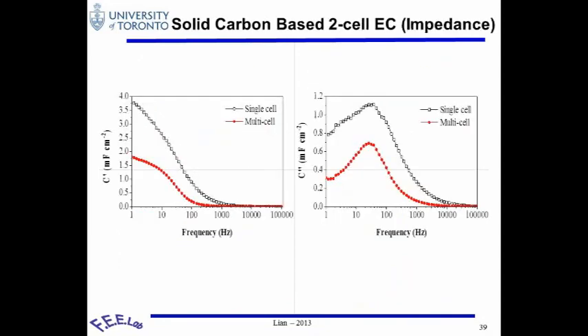This is just the last graph that I want to show you: when you have one device, you do have a high capacitance, but when you have 2 devices in series, you can expect that the device should have half the capacitance, which is the red one. However, in terms of time constant, they still stay very much the same. That shows you that even with stacking, you didn't increase the resistance that much.